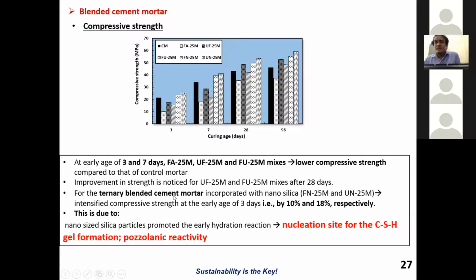However, for the ternary blended cement mortars incorporated with nanosilica, even though they are in a very small percentage, you can see the early age strength increasing at 3 days by 10% and 18% respectively, compared to the control mortar. What can the reaction be? Nanosilica particles promoted the early hydration reaction. They can be nucleation sites for C-S-H formation and give more pozzolanic reactivity.